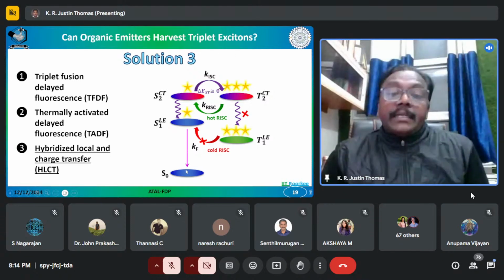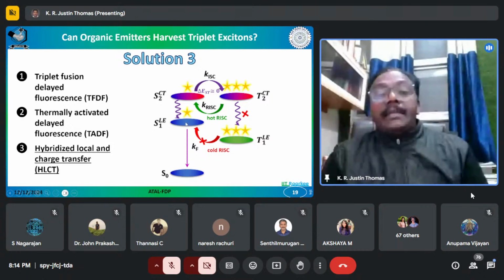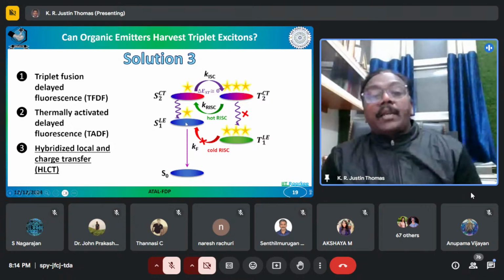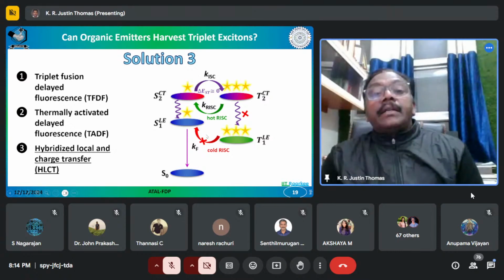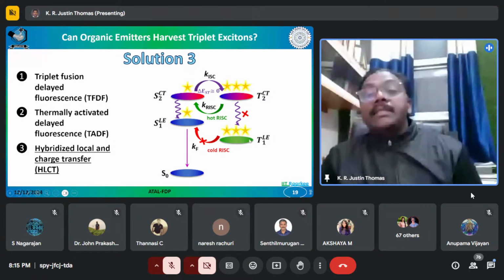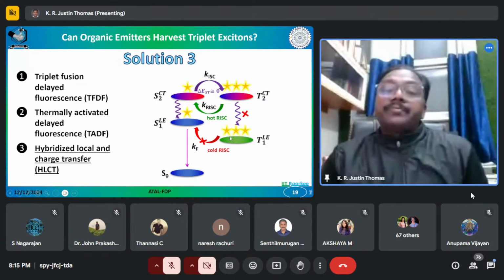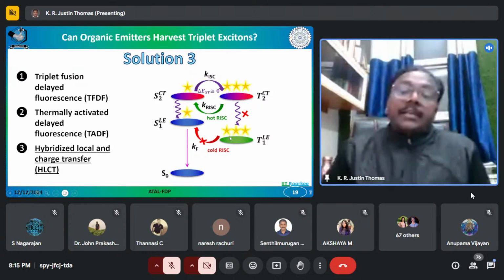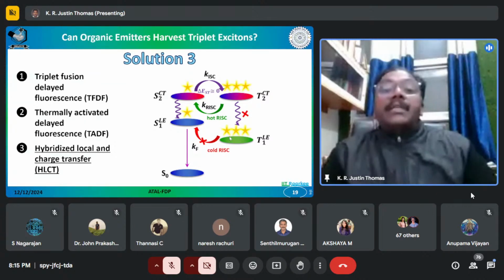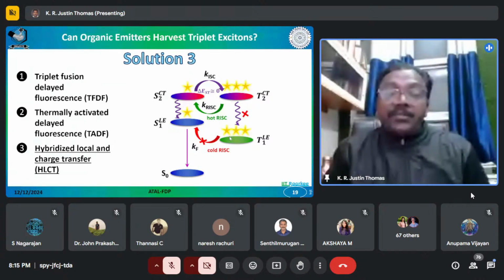So when a molecule is excited to its singlet excited state, which is predominantly a local excited state, it cannot undergo intersystem crossing from the singlet excited state because the triplet excited state, which is also predominantly LE in character, is too far away. That is, the gap between S1 and T1 is very high. So you cannot have reverse intersystem crossing in these kinds of molecules. This is the general characteristic of organic emitters, which generally have a pi to pi star excited state.